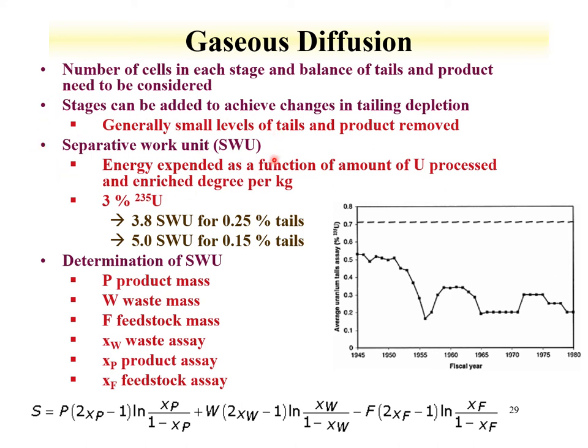The separative work unit (SWU) is the unit used to evaluate the relative energy for enrichment—energy expended per kilogram of uranium processed and enriched to a given degree. For instance, to reach 3% uranium-235 with tails at 0.25%, one needs 3.8 SWU per kg. The SWU equation is a function of product mass, waste mass, feedstock mass, and the isotopic fractions.